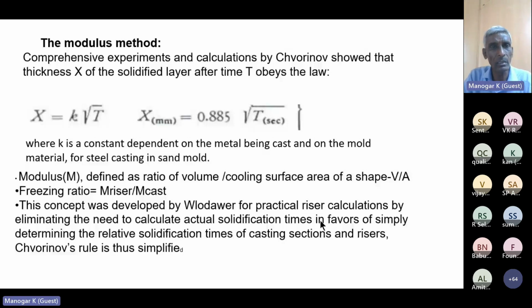As per Chvorinov, the solidifying layer obeys the rule x equals k square root of t, where k is a constant depending upon the boundary conditions. Modulus is the ratio of volume and surface cooling area. Next, freezing ratio is the ratio of modulus of riser and casting. This concept was developed by Wlodawer for practical riser calculation by eliminating the need to calculate actual solidification times.